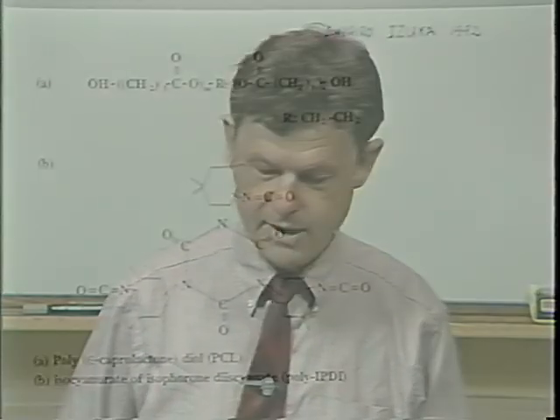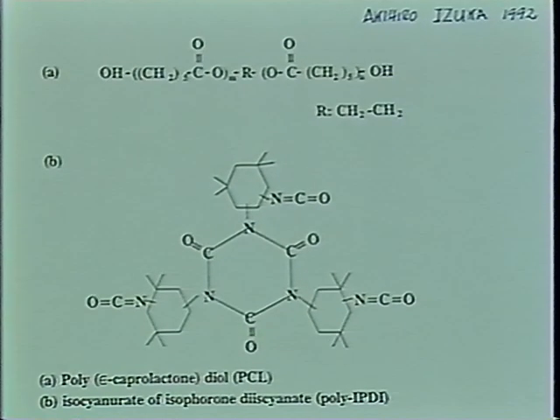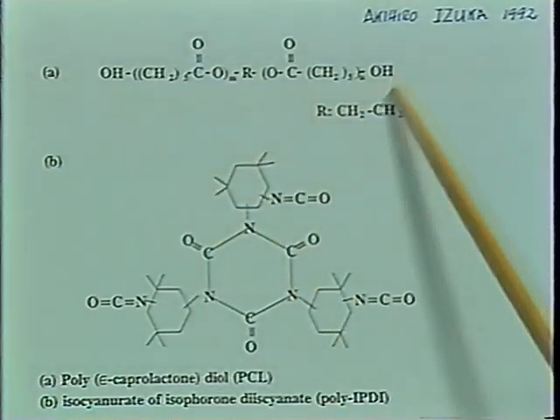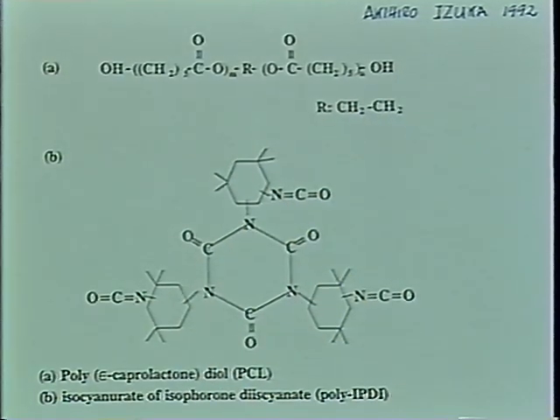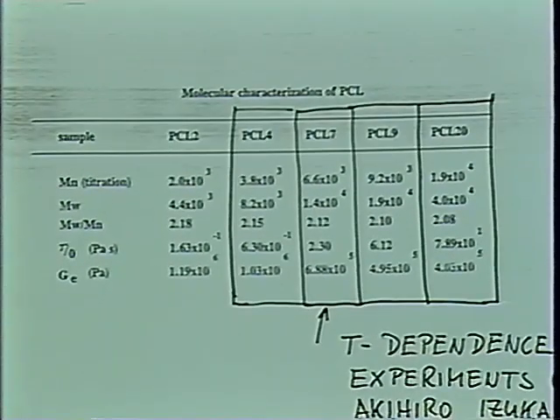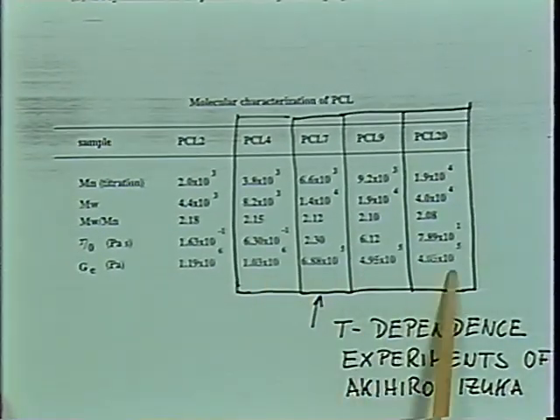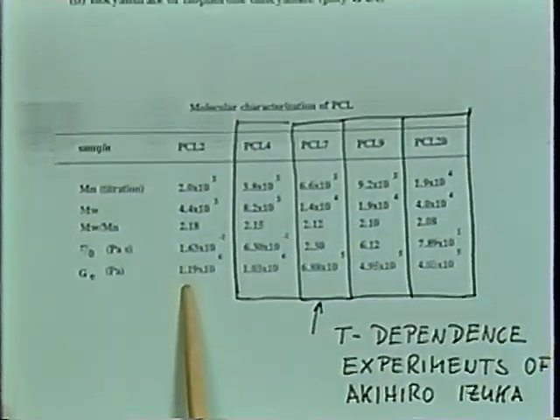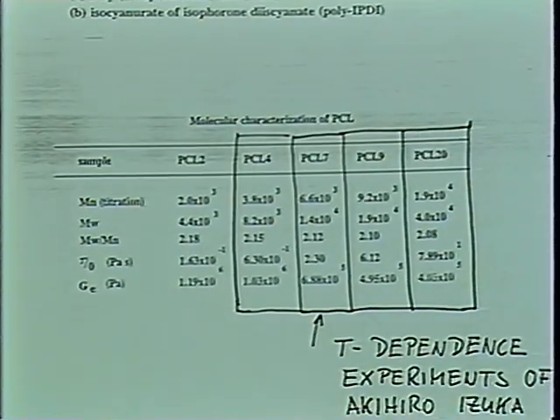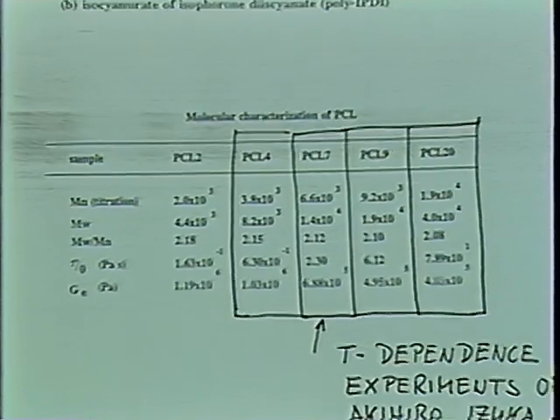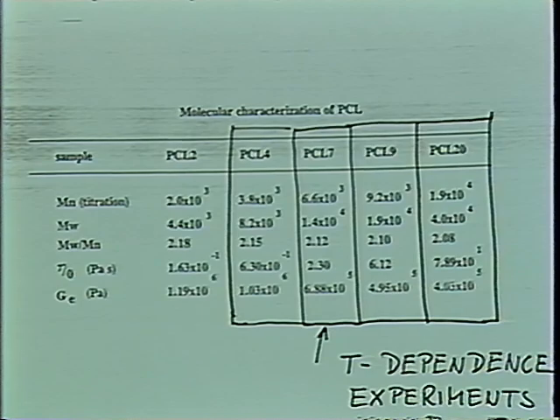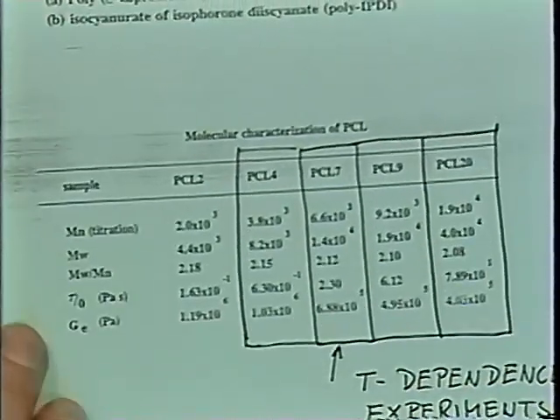Akihiro Iizuka studied that same problem here. He looked at his caprolactone gels, long linear chains with 3 functional crosslinker, at several different temperatures. You saw this table before. He took only the 4 higher molecular weight samples. The lowest molecular weight sample didn't give enough stress response. This molecular weight was too low, and then when he went to high temperatures, he just couldn't measure anything anymore. So that's why he excluded that. And the precursor viscosity followed an Arrhenius relation.